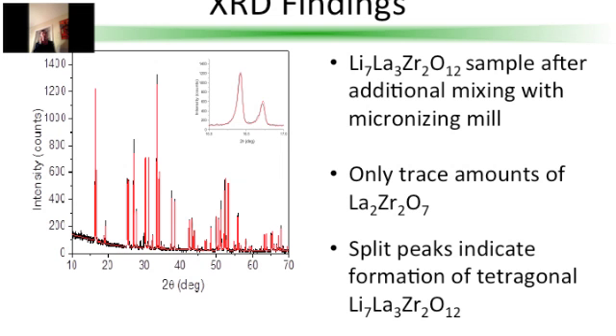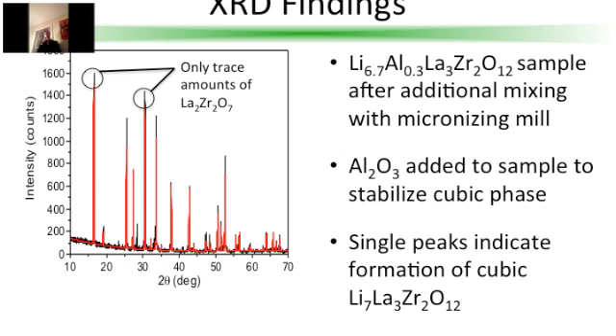Now, if you recall, I wanted to synthesize the cubic phase of this material, so I had to tweak the conditions even more. So I went back to the literature and discovered that researchers still don't know how to synthesize cubic phase pure lithium lanthanum zirconate. However, many researchers noted that it is possible to synthesize a very close structure to cubic lithium lanthanum zirconate by contaminating the samples with aluminum. And at first this puzzled me because I thought that if we're trying to synthesize lithium lanthanum zirconate, why would we want to contaminate the samples with aluminum to get a completely different compound?